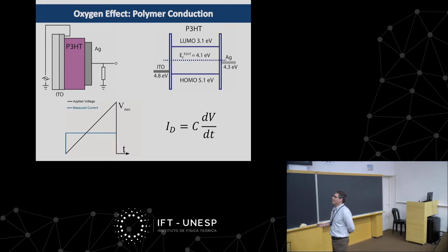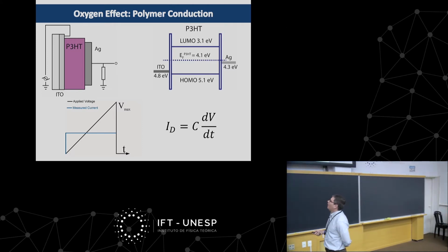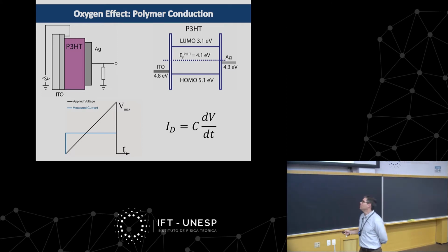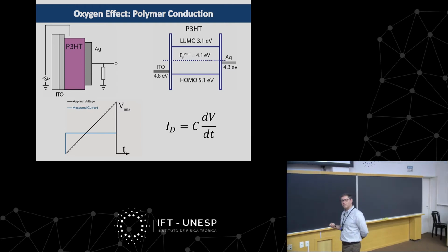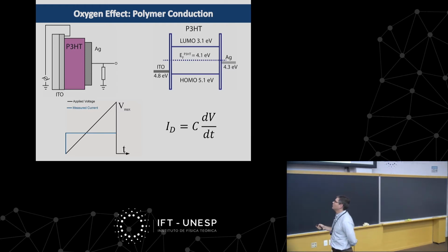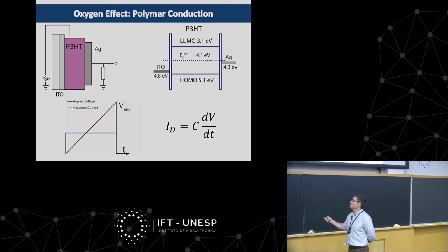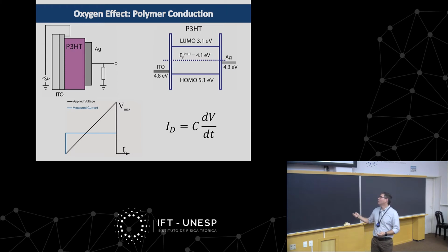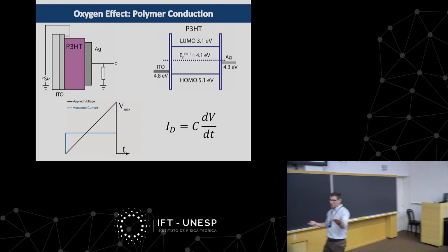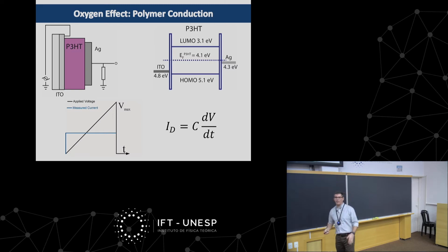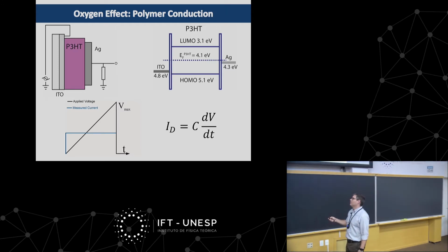And the way we actually measured the electrical property of this film is by simply applying a linearly increasing voltage. The reason we do a linearly increasing voltage is because this is basically a capacitor. So you have electrodes separated by a dielectric. A capacitor gives a capacitive response, what we call displacement current, which is basically C, the capacitance, times dV/dt, which is the derivative of voltage in time. So by applying a linearly increasing voltage, this displacement current is basically constant.